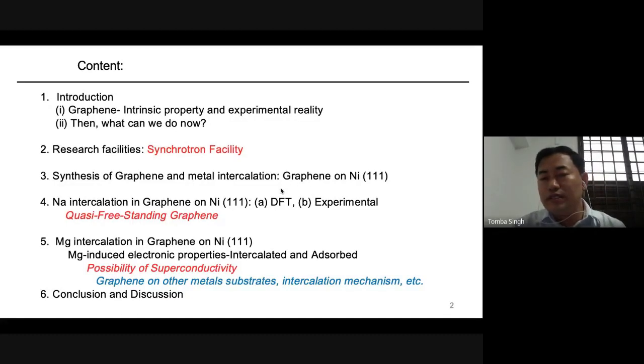This synthesized graphene can be modified using a technique called intercalation. And we have theoretical support from the density functional theory, and we want to compare with our experimental data here. The target of this work is we want to get a quasi-freestanding graphene, that means really floating graphene, without interaction with the substrate where it stands. We use a different material, magnesium, for intercalation again, but the target is different. Here, we would like to induce superconductivity in the graphene.